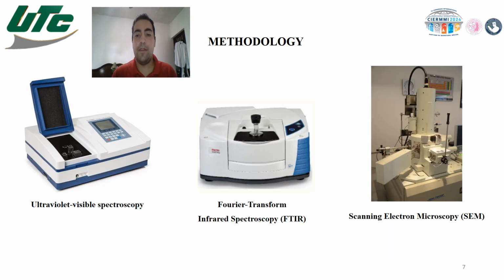Continued with the characterization. The first, ultraviolet-visible spectroscopy. The presence of curcumin in its bioactive form within the nanoparticles was confirmed using UV spectroscopy, a technique that allowed the analysis of molecular interaction between curcumin and additional components such as beta-glucan and vitamin C, D3, and zinc. This analysis was conducted using a UV spectrophotometer. The second characterization is Fourier transform infrared spectroscopy, or FTIR. The incorporation of beta-glucan, vitamins, and zinc was confirmed through FTIR analysis.